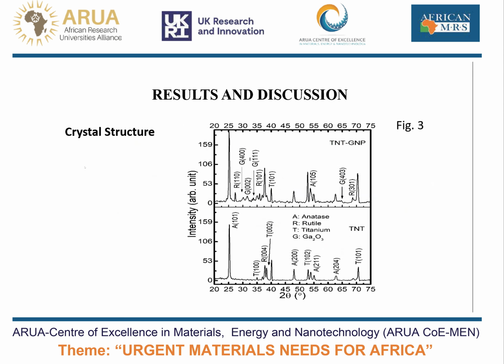Results. Figure 3 here is the crystal structure of the prepared materials. The first X-ray diffraction pattern is the XRD pattern of the titanium oxide nanotube that was obtained at 550 degrees Celsius without being modified, while pattern 2, which is the TNT GNP, is the XRD pattern of the titanium oxide nanotube that is decorated with gallium oxide.